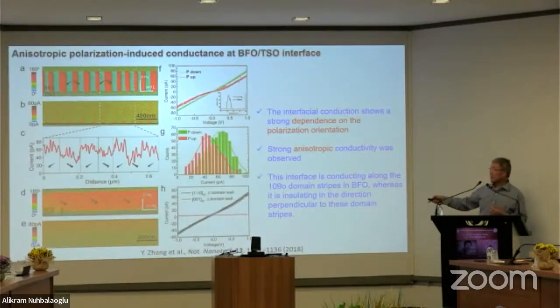You want to quickly introduce the data. That's really exciting. So this is a polar oxide ferroelectric grown on a standard substrate insulator. And the interface you can see is very conductive. This is high intensity. Dark is high intensity, conductive. And then the conductivity also changes from one domain to another domain. You can see it's alternating, and this is shown by the line profile.